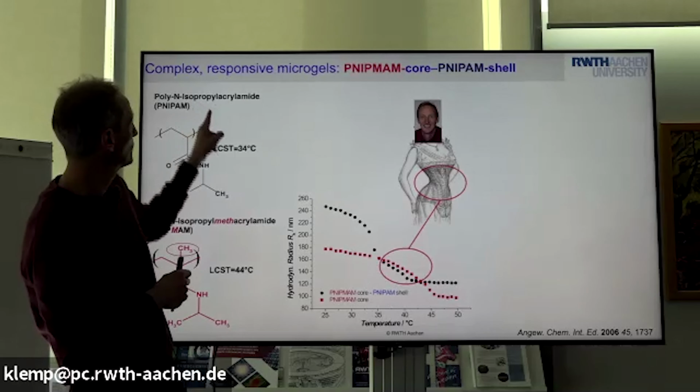Now, that shows it's important that the outer layer, the shell, is cross-linked. So it's basically as tight as one swells, the system cannot swell because it has a shell which is still collapsed. Yeah? Now you might argue that my line of thought is not really convincing because what I discuss here is only the outer size that we measure, the hydrodynamic radius. Absolutely true, but we have done the neutron scattering, we have seen the neutron scattering curves, and that fits with the core shell model. So we are very confident that this is really the internal structure as I described before.